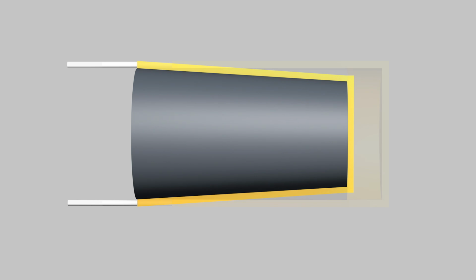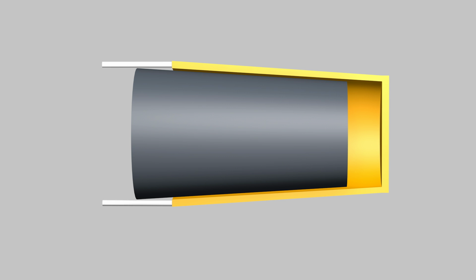Another very important aspect of mold design is the draft angle. If a part has walls that are exactly 90 degrees, it will be very difficult to eject for a number of reasons. When the part is ejected, its inner walls will scrape against the core half of the mold. Also, a vacuum will be created since air cannot enter. However, if the walls are slightly tapered, even just 1 or 2 degrees, it becomes much easier for the part to be removed. Because once the part is moved just slightly, the walls are no longer in contact with the cavity and air can rush in.